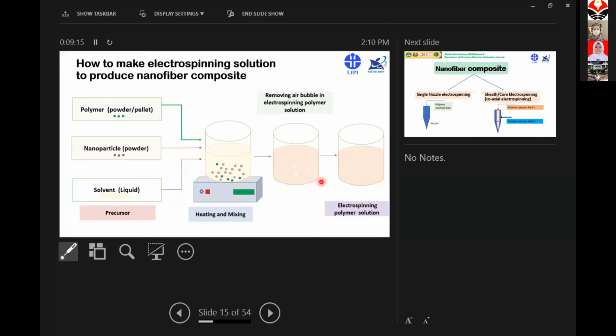Okay, the important point when making nanofiber by electrospinning is how to make a homogeneous electrospinning solution. For example, if we want to make a polymer nanofiber composite, first we use polymer in powder or pellet form, nanoparticle in powder form, and solvent. We mix it by mixing and heating, and wait until all the polymer is dissolved in the solvent. After that, we must remove the air bubbles in the electrospinning solution. Then we can use the polymer solution to make nanofiber composite.